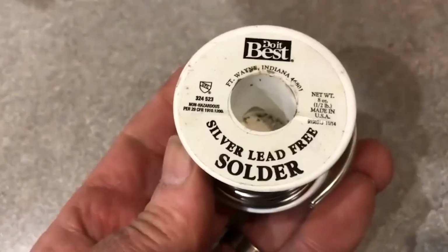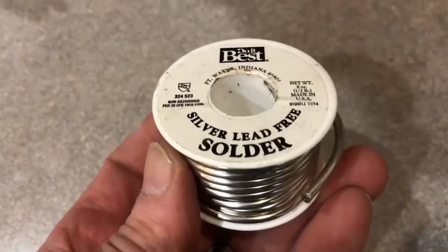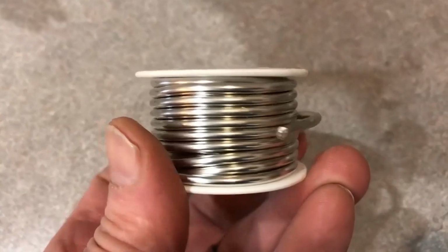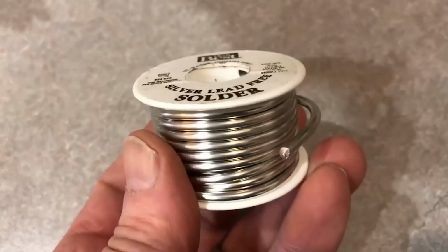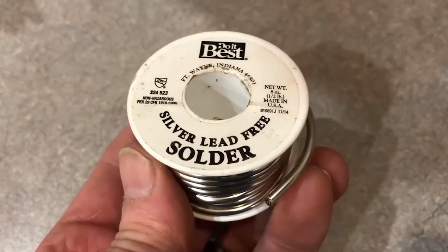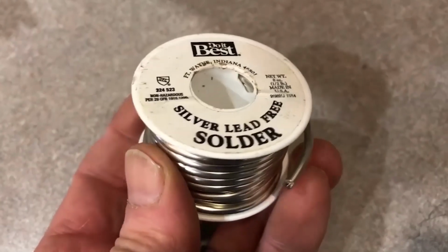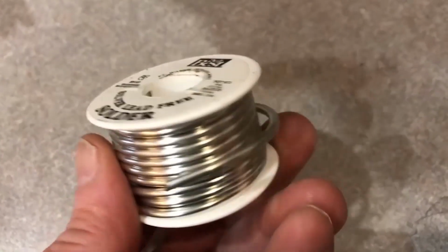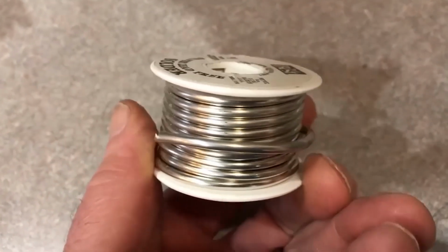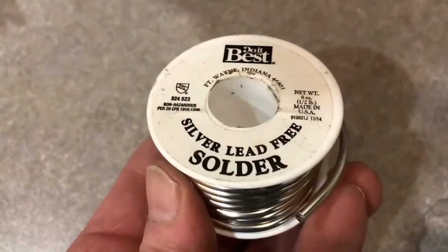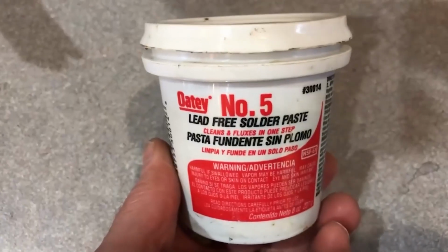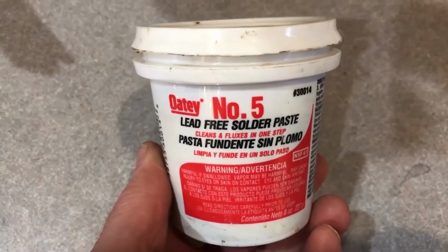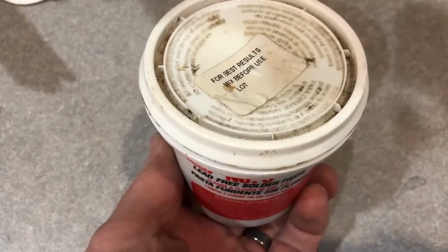Here is some lead-free solder. This is often used to solder copper pipe used for plumbing in buildings. The lead-free part is important, as the lead in leaded solder will slowly leach into the water flowing through the pipes. This solder is also stronger and has a higher melting point than leaded solder, about 422 degrees Fahrenheit. One drawback to lead-free solder is that the correct flux contains acid to help strip the metal of oxidation at the higher soldering temperature.